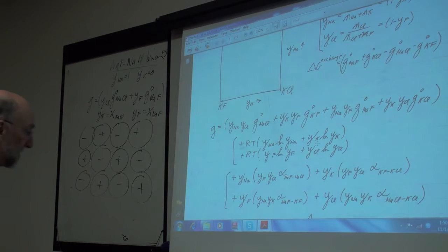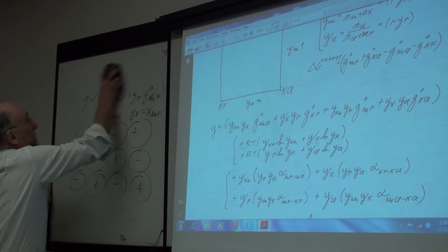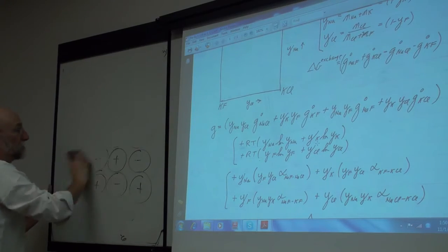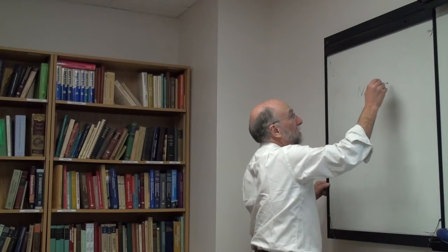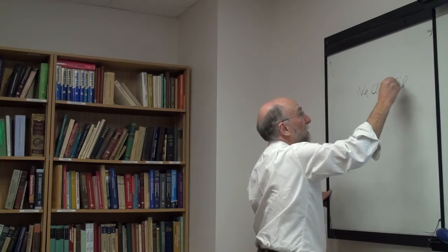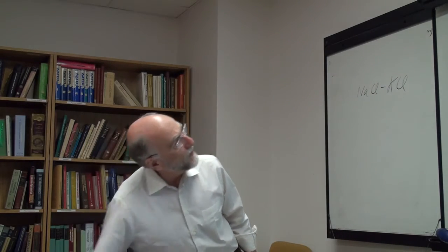Okay, first of all, this is the sublattice model, the standard way, compound energy formalism. This is what's used by CALPHAD, SGTE, Thermo-Calc, everybody. This is the 2 sublattice equivalent of the polynomial model. Random mixing. This is the Bragg-Williams model in 2 sublattices, what we're doing. So it has to reduce to the Bragg-Williams model in every binary system. Okay, so let's take, say, the sodium chloride, potassium chloride system. Take the binary sodium chloride, potassium chloride system over here.